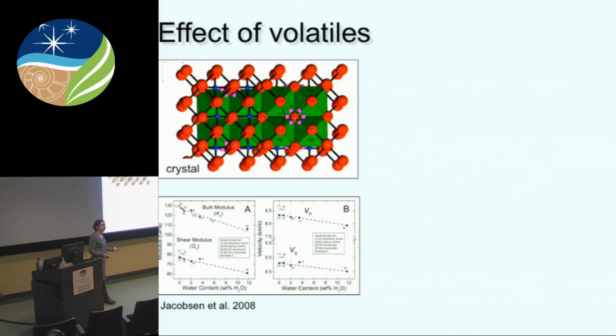Okay, what about the effect of volatiles on these materials? Well, it turns out, again, it's very different. In crystalline silicates, you incorporate volatiles into the crystal structure. Here's an example of water being incorporated into one of the olivine polymorphs. To charge balance the volatile, you have to balance it with vacancies. So this not only expands out the structure, but with the vacancies you also have a softer material. This is bulk modulus or velocity as a function of water content, and what we expect to see is a decrease. So water or volatiles would soften a crystalline silicate.